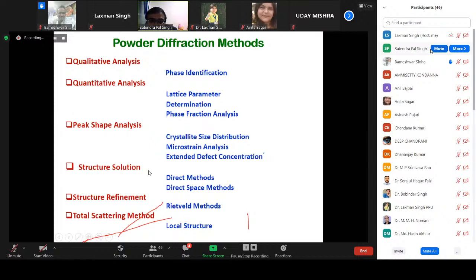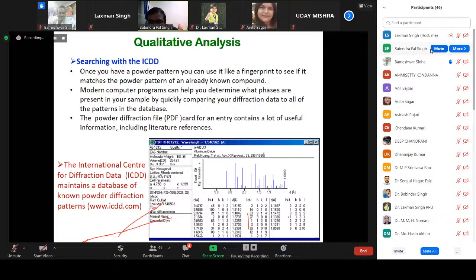pattern, we can have a structure solution using direct methods, and the structure refinement using Rietveld methods. With total scattering methods, we can also find the local structures using the PDF, pair distribution functions. So all these powder reflections are helpful for qualitative and quantitative analysis and all the structural information, the defects, disorders, the crystallite size, and so on. So many pieces of information can be extracted from the powder XRD pattern.